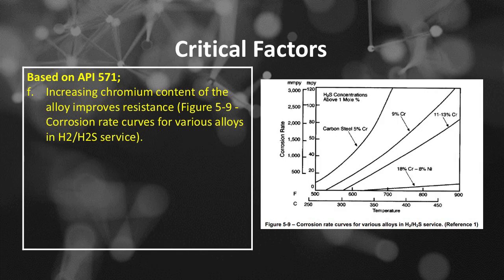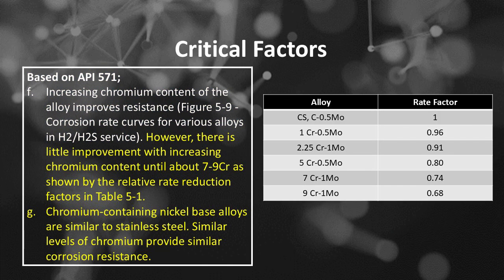Number F, increasing chromium content of the alloy improves resistance. See Figure 5.9, corrosion rate curves for various alloys in hydrogen or H2 and hydrogen sulfide or H₂S corrosion service. However, there is little improvement with increasing chromium content until about 7 to 9% of chromium as shown by the relative rate reduction factors in Table 5.1.